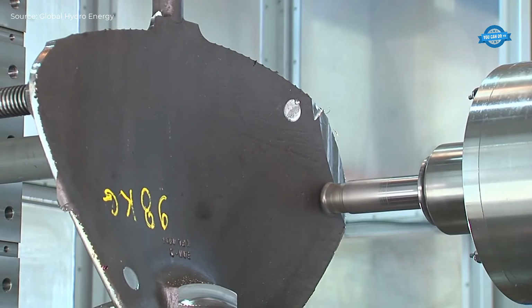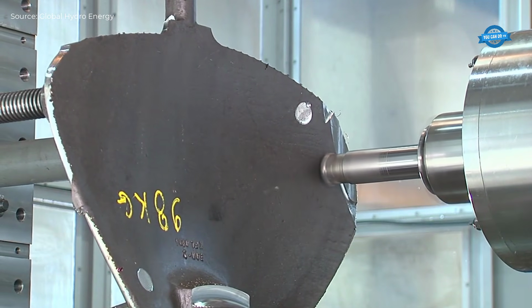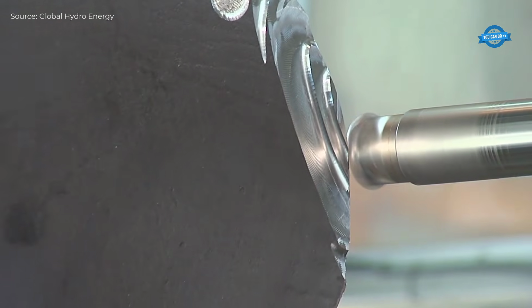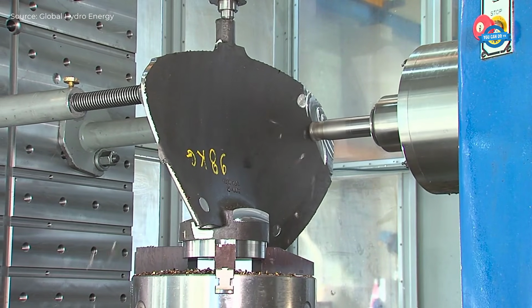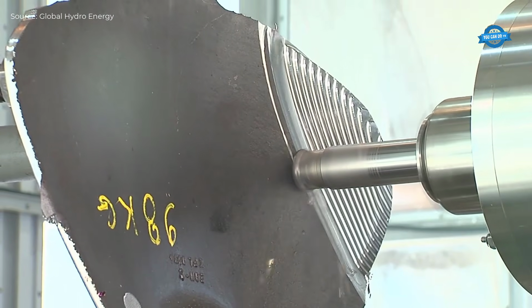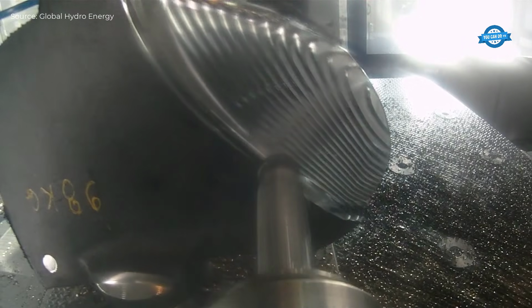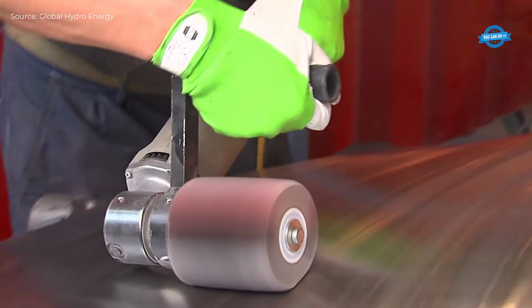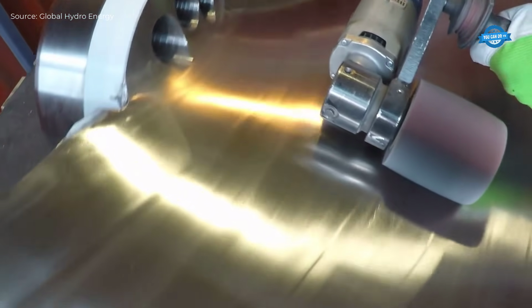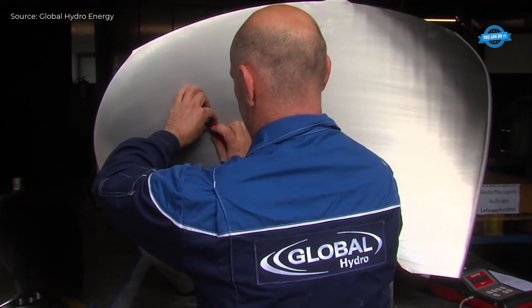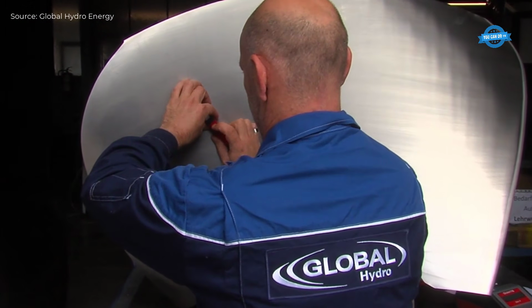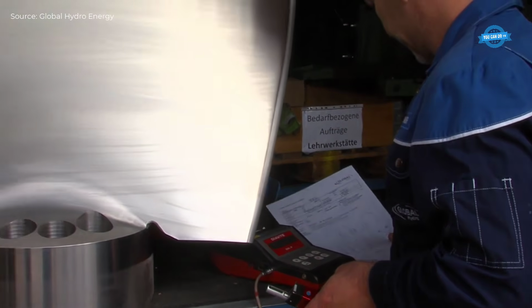The manufacturing process for the Kaplan runner blades is labor-intensive and precise. Each blade undergoes a meticulous milling process that can take up to 60 hours, depending on the size and material of the turbine. The blade surfaces are polished by hand after milling to achieve a smooth finish, and each blade is inspected according to ISO standards to ensure it meets stringent quality requirements. Surface crack and pore testing is performed using two-color dye penetration techniques as per DIN ISO regulations.